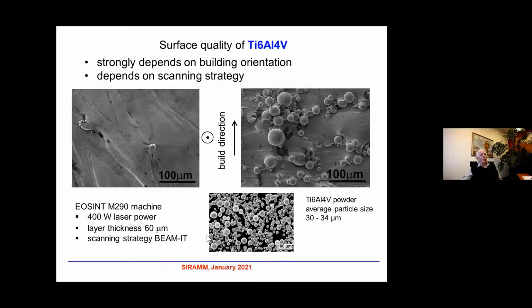The powder which was used for the component is shown here. You can see that there are particles of different diameter. The average particle size is nearly 30 to 34 microns. The surface of the component which is perpendicular to the build direction, it means this surface on the left-hand side, is relatively smooth. Here you can see traces of the laser pools, how the laser moved, and the surface quality is relatively good.